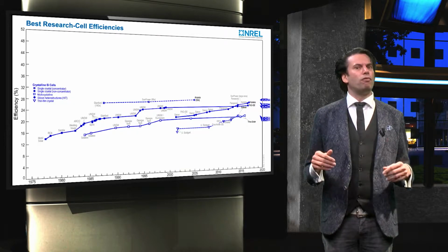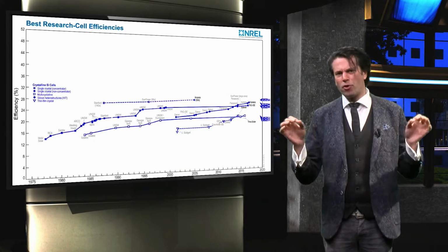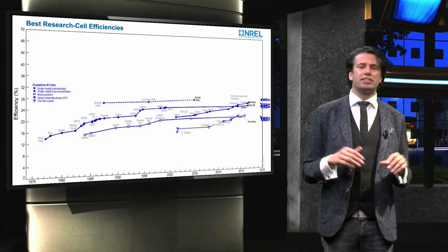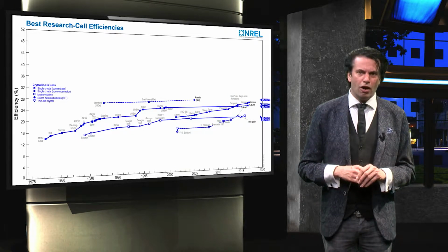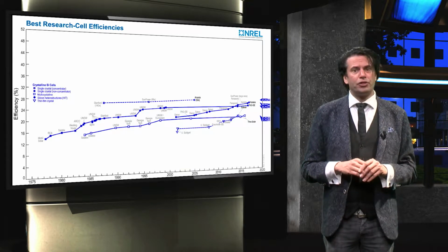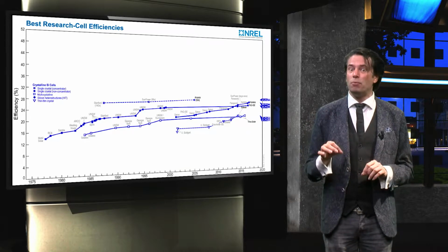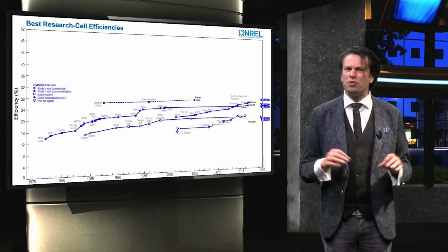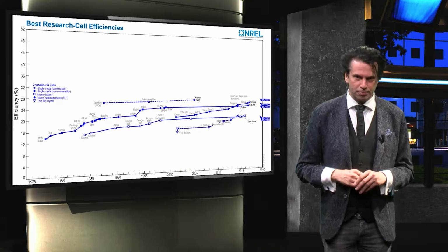The efficiencies of multicrystalline silicon-based PV cells are approaching 22%. Trina Solar has demonstrated P-type multicrystalline PERC cells having an efficiency of 21.3% for typical 6-inch wafers. At the 33rd European PVSEC conference in Amsterdam, Fraunhofer ISE presented an N-type multicrystalline solar cell with a 22.3% efficiency based on high performance wafers, but with a smaller area of only 2 by 2 centimeters.